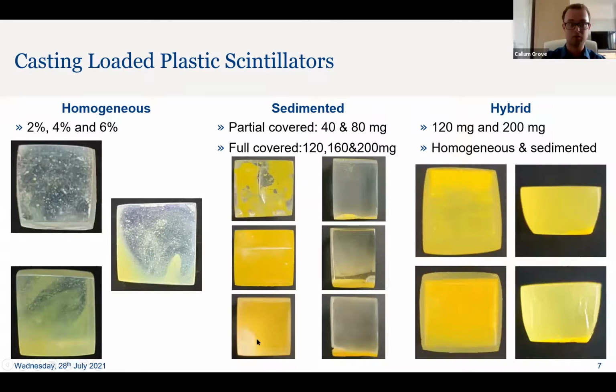The 3 batches that we have homogeneous are 3 different loadings: 2%, 4%, and 6%. The 4% wasn't as successful. There's a significant clumping of quantum dots on one side of the scintillator rather than relatively well homogeneously dispersed throughout the scintillator as the 2 and 6% are.